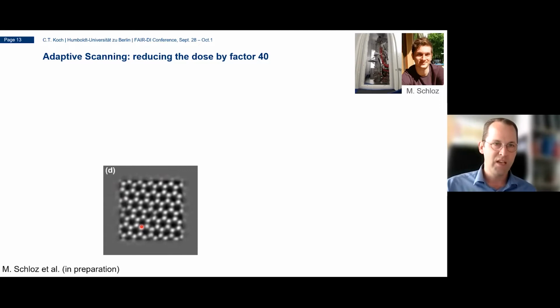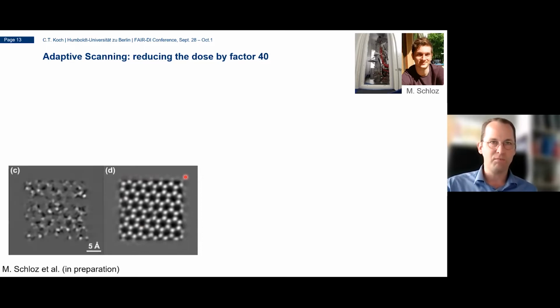of the atomic positions. Now, there is, of course, a trade-off. You don't want to position the beam too closely and collect too many diffraction patterns for too long, because you may damage your material. And there are these techniques called compressed sensing, where you only position your beam randomly and try to still do reconstruction with that information. And this would be a reconstruction from a compressed sensing acquisition scheme, where you have random positions of your probe, and you only have a factor of 40 fewer probe positions. So your material doesn't see as many electrons, it may survive longer, but your reconstruction is actually not very good.